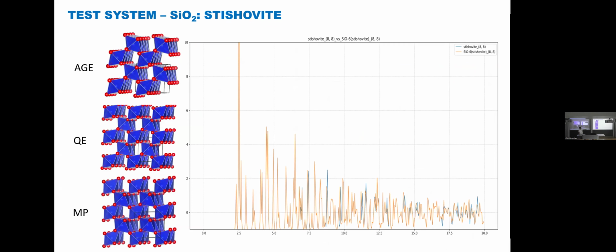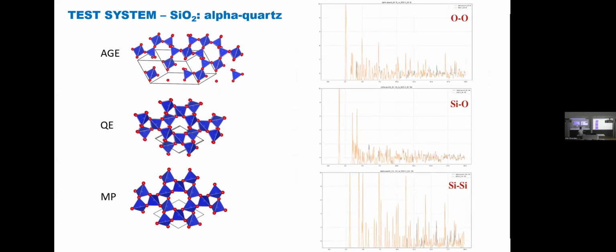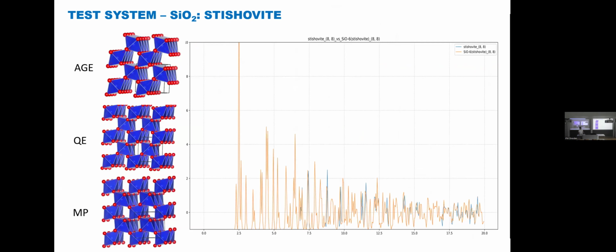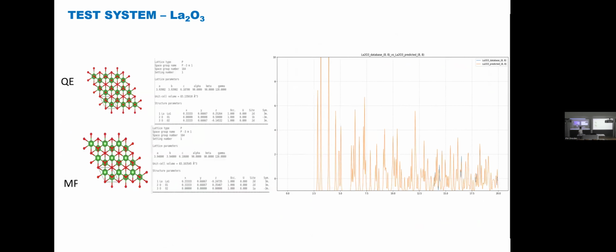Just another example, for stishovite. It is 6-coordinated silica, while here this is 4-coordinated. So we have the tetrahedron as structural blocks here, but there we have the octahedron as structural blocks, and we also got the structure. It also matches well with the reference structure. In our diploma we have dozens of pages with this information.